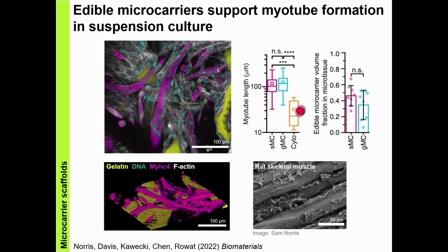Now, just for comparison, here's an image of some rat skeletal muscle, and you can see that these muscle fibers are very long and straight, so we're not quite replicating exactly the structure of the skeletal muscle, but we found that these structures were more aligned and showed longer myotubes than for the Cytodex bead situation.